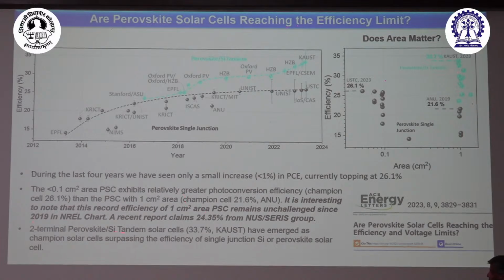Okay. Again, tandem solar cells have reached up to 33.7% in this one. And this is where, if you plot efficiency versus the area, there are two classes. One is about 1 centimeter square, this is what we started with earlier. And this is the tandem solar cell, whereas these are single junction perovskite. You can see here, they were all at 0.1, and the recent ones are lower area. So the question is, is this increase because they decreased the size, right? It is not the whole performance.